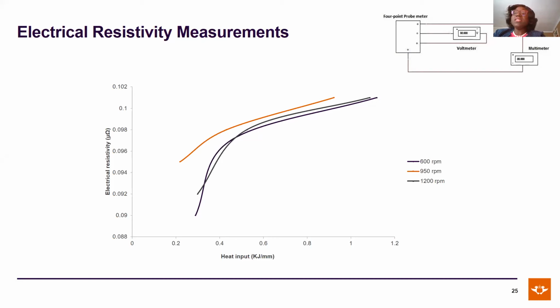Because the heat input into the welds is correlated to the formation of the intermetallic compounds, in the sense that intermetallic compounds are formed at high temperatures. So the electrical resistivity was correlated to the heat input to be able to have an idea of what is going on in the welds. You will observe from the data before us this afternoon that the electrical resistivity is very, very low in micro-ohms, and that is the data we have here.